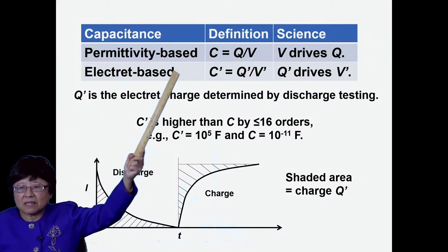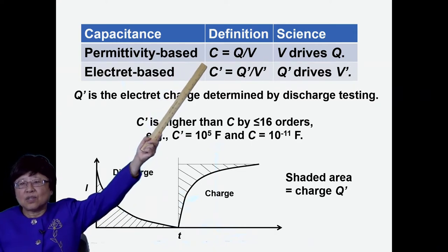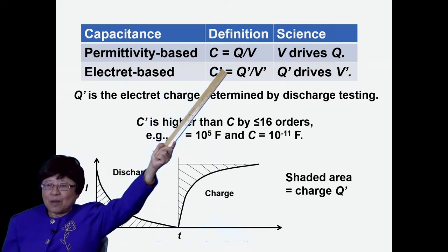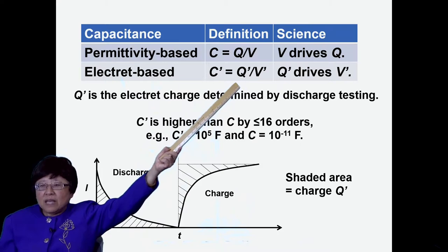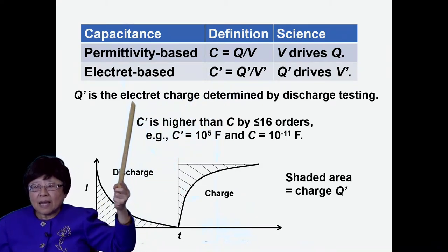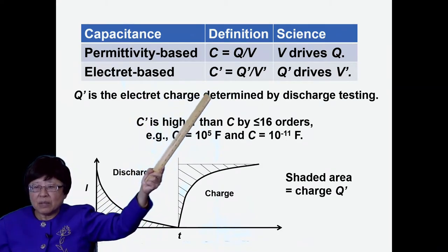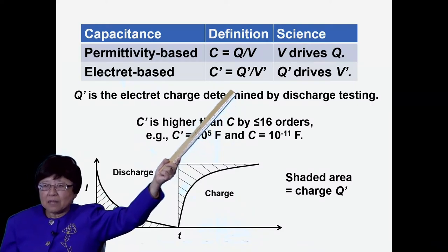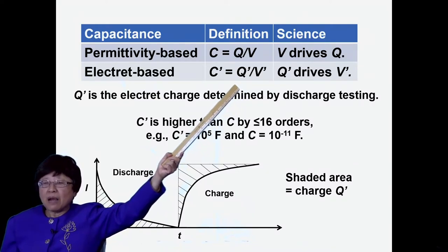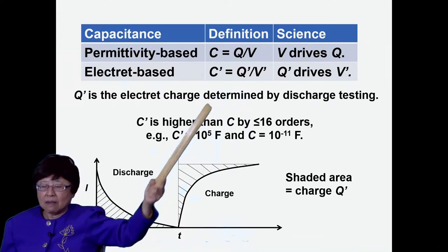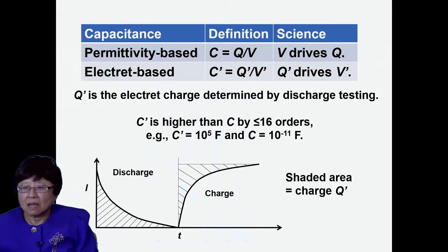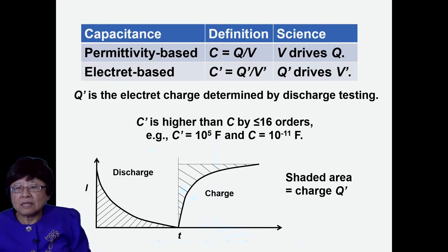The permittivity-based capacitance, C, is Q over V, well known, with V driving the Q. But the electret-based capacitance, which I call C prime, is Q prime, the electret charge, divided by V prime, the electret voltage, with Q prime driving V prime. And Q prime is determined by integration of that discharge curve.